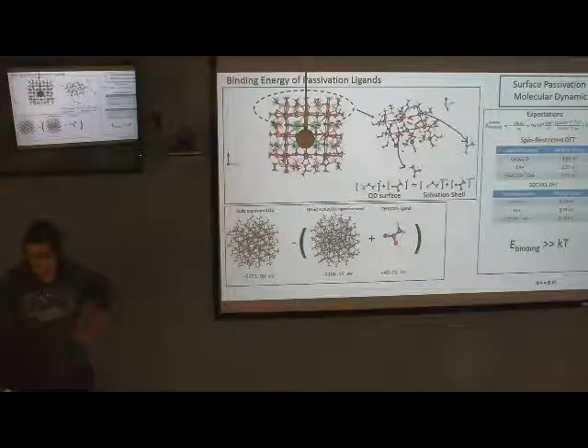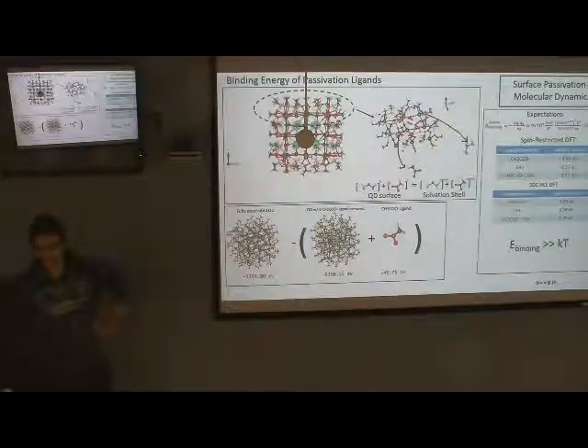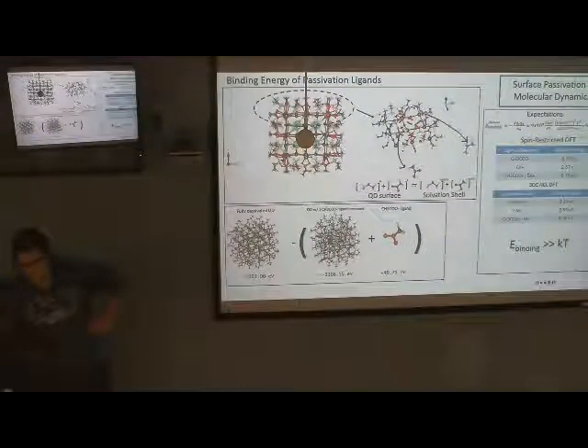The first thing to think about is that if the ligands are going to pop off, they would have to have a pretty low binding energy. So a natural thing would be to look at binding energies of the ligands to the perovskite quantum dot surface. This top image just shows spaces on the quantum dot that I removed ligands from. Looking at this top surface, I altered it a little bit, and you can see it took one of the acid groups off from the centralmost position, because it's least affected by other ligands, so you get a better idea of just removing that ligand without any correlation effects from other ligands. And then I also removed an amine that's adjacent to it, covering one of the faces.